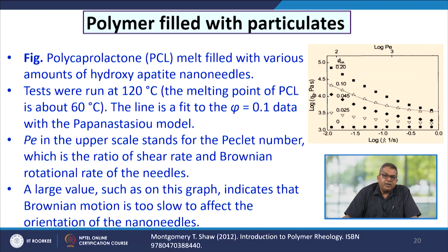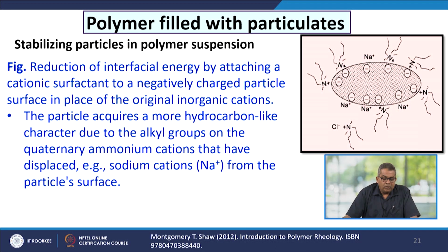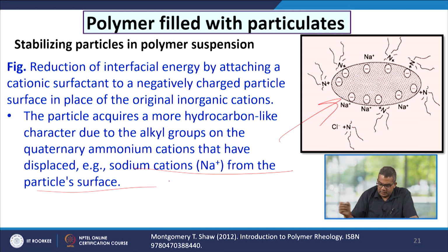Now, if we talk about stabilizing particles in a polymer suspension, there is the reduction of interfacial energy by attaching a cationic surfactant to a negatively charged particle surface in place of the original inorganic cations. The particle acquires a more hydrocarbon-like character due to the alkyl groups on the quaternary ammonium cation that have displaced the sodium cation from the particle's surface.